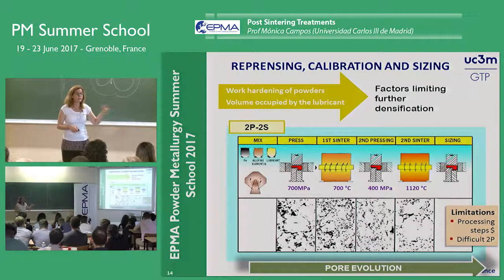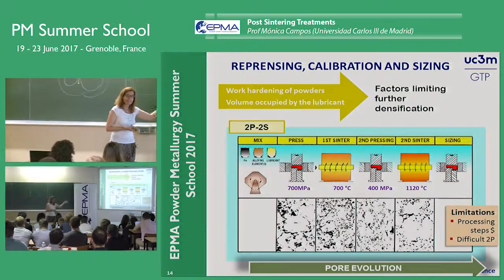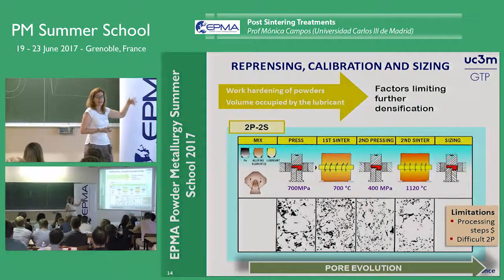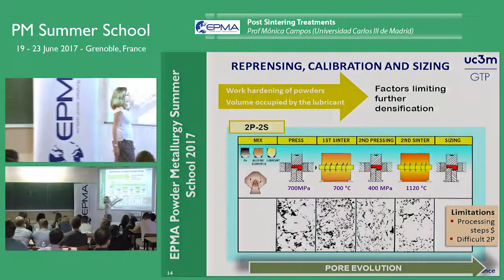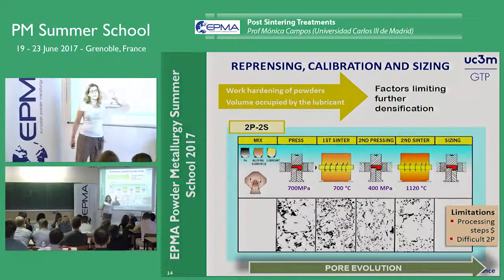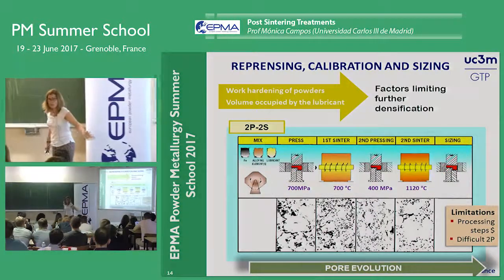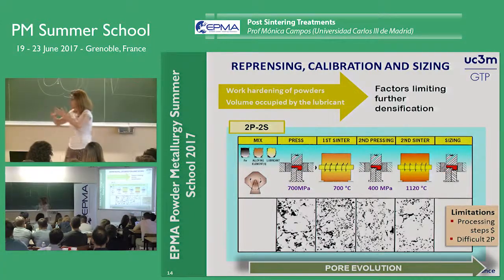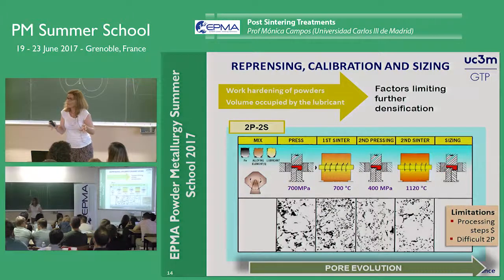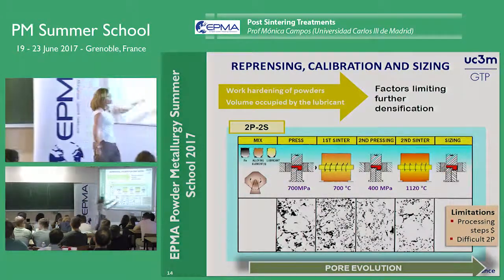At lower temperature than you should expect. What will happen if I sinter in that first step at 1120 or 1150 degrees? If I sinter here at higher temperatures, carbon diffuses into our component and forms, depending on the cooling rate, pearlite, bainite, martensite, depending on the chemistry. And then we try to take this part and press again.